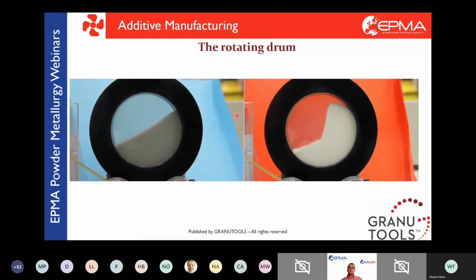On the left video, the blue video, when the drum is rotating, if the grain is too high regarding the flowing angle of the powder, it will detach itself and flow, creating a flow inside the drum which makes a very constant interface. The interface is barely moving.